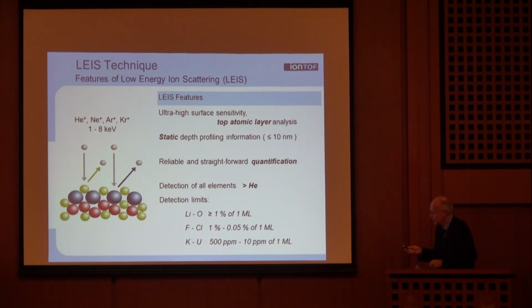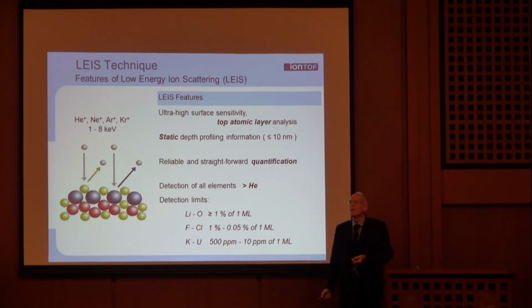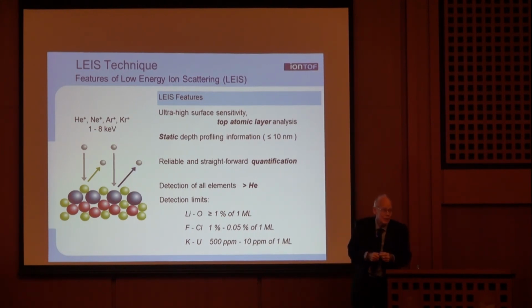Okay, summary for the moment. First summary is outermost layer, deeper layers, detection limits for the top layer. Light elements, we are not so very sensitive. So for lithium, it's only a few percent. But if you get to the heavier ones, say like platinum, about 10 to the minus 5 of a monolayer, so 10 parts per million of one atomic layer, we can see for heavy elements.